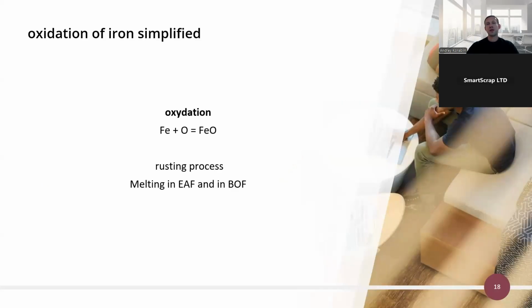In electric arc furnace, oxygen is blown into the furnace as an additional energy source to increase melting speed. While electricity provides the primary heat through electrodes, additional heating is provided by oxygen burners to optimize furnace operation. As oxygen is supplied, some of the iron in electric arc furnace oxidizes, which is why electric arc furnace slag often has a high content of iron oxides.